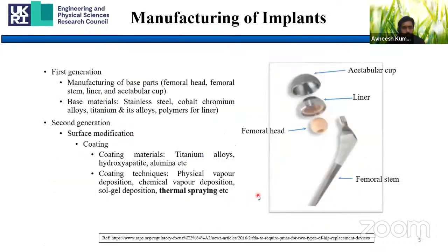The manufacturing of these implants is basically a two-step process. In the first step, they prepare the base part of the implants using some advanced manufacturing techniques like additive manufacturing or maybe casting processes. For that, usually people have used stainless steel, cobalt, chromium, titanium, and the like, and some polymers also, like ultra high molecular weight polyethylene and highly cross-linked polyethylene. Then to further enhance the properties of the surface of these implants, surface modification techniques are used. In surface modification, they have tried some coating of these implants in order to get better tribological properties.